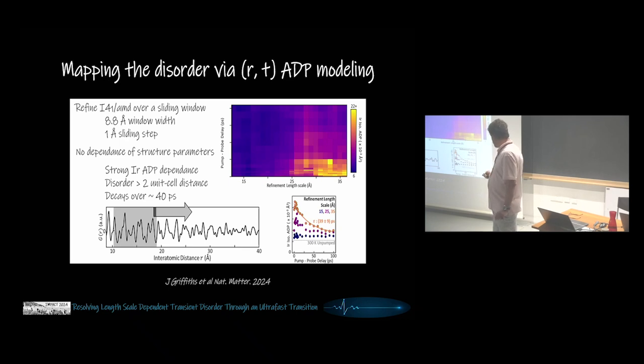And so what you do see is that locally, meaning for the short length scales, you do not actually have an enhanced value of this ADP. It's of the order of 6 times 10 to the minus 3 angstrom squared, which is what you expect at the 150 Kelvin temperature in equilibrium. However, at the longer length scales, you do see that this parameter gets enhanced by 3.5 times for short delay times. And then this actually relaxes as you go towards longer delay times. So that's reflected in this couple of curves, depending on the range. And you can extract from there a time constant of the order of 40 picoseconds.